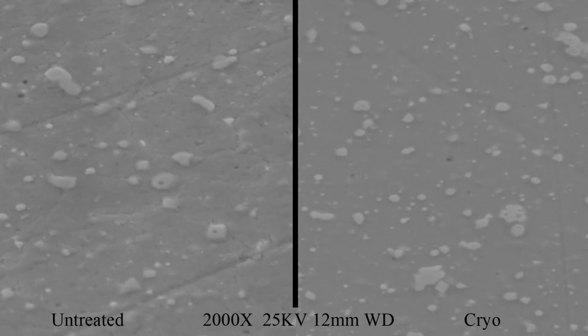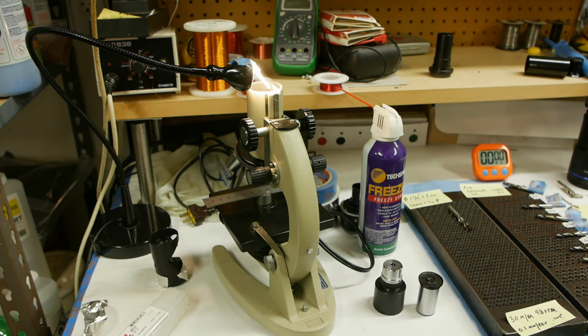So I mentioned that you need at least 0.5% carbon in the steel to harden it, and a lot of that carbon forms these little hard particles that kind of hold the matrix together, right? It's kind of like concrete and cement. The strength of the material comes from the little rocks in it, and the cement itself is okay in strength, but it's really the rocks that give it the ability to be abrasion resistant. Same thing with this steel. These carbide precipitates are important for keeping the steel very strong.